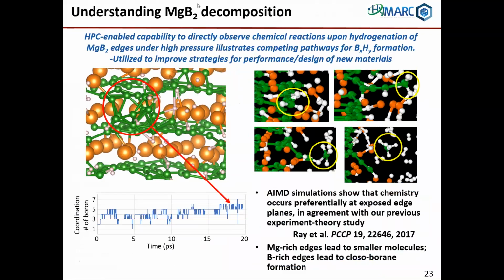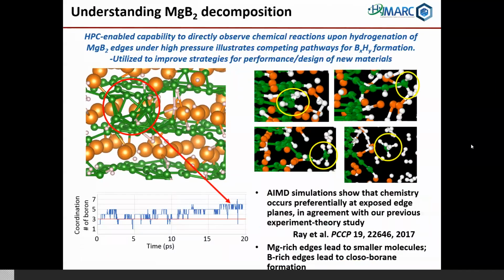I mentioned borohydrides. Borohydrides are attractive because they're light and their gravimetric and volumetric capacities can be very competitive, but they are also incredibly complex materials. Taking magnesium borohydride as our starting point, these materials have complex decompositions that produce molecular species, closoboranes, that are kinetic intermediates, and it was baffling for years trying to figure out how to stop this from happening, what was controlling this formation. So what you see here is some modeling that we did, and this again was correlated with experiments that allowed us to look at the very early stages of the rehydrogenation of magnesium diboride.